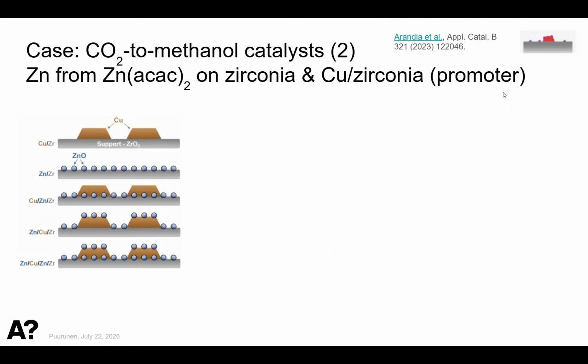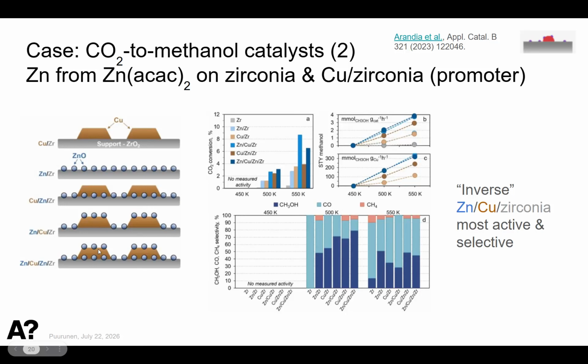And quickly about catalytic testing, published in Applied Catalysis B. We tested different locations for zinc. We also tested copper on zirconia without zinc, and zinc on zirconia without copper, and then various combinations: whether we place the zinc before copper impregnation, or impregnate copper first and then add the zinc. In one case we did both. Long story short, we found that adding zinc as the last step was favorable. We had both the highest conversion of CO2 and the best yields, best production rate of methanol in those cases. The blue points here represent the cases where zinc was last on copper. And also the selectivity was best.